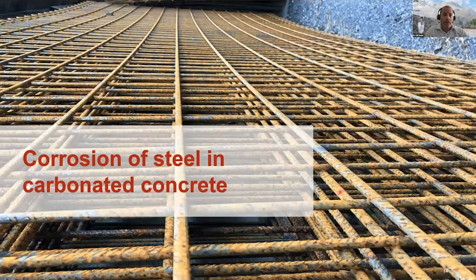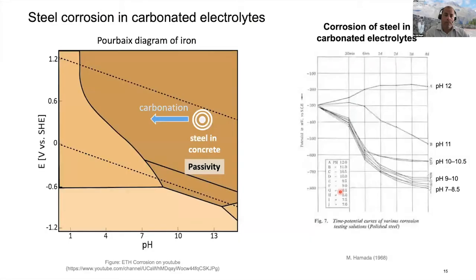Now I would like to move on and spend a few minutes on corrosion of steel in carbonated concrete, which is a very different process, but again also here the interfacial zone of the steel and concrete plays an important role. Steel in concrete is basically well known to be protected against corrosion because it is passive at very high pH. But when the concrete carbonates, the alkalinity is lost so that the pH actually decreases, and that may increase the risk of depassivation and then later on corrosion.